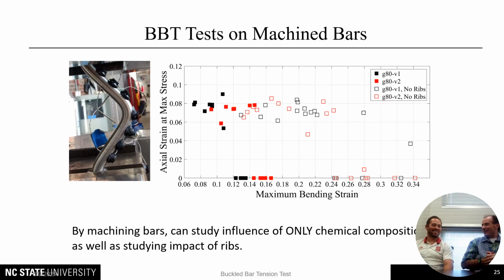Then you did these, which are interesting. Well, I think we took that, we saw there were lower stress concentrations. Those bars did better in the buckled bar tension test, and so the critical bending strain was higher. So we thought, well, what if there are no stress concentrations at all?